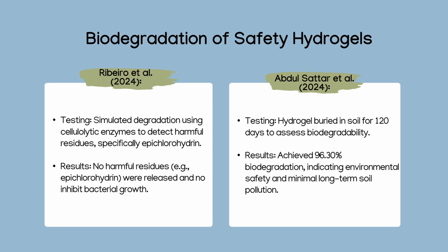Also, in the Satar study in 2024, he buried hydrogel in soil for 120 days to assess the biodegradability. He found that about 96.30% of the hydrogel was biodegraded, indicating environmental safety and minimal long-term soil pollution.